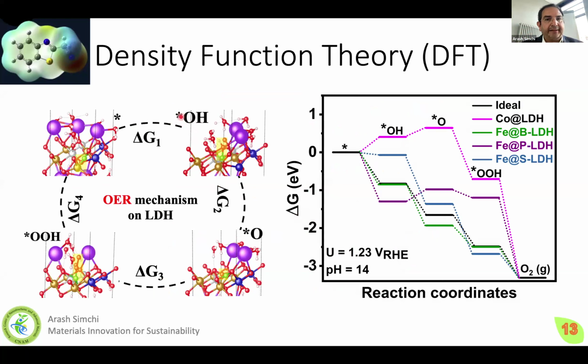OH star adsorbs on the surface, and then oxygen star is produced and makes it OOH, and then oxygen is created. So there is some energy behind that for the oxygen evolution reaction. And then we can calculate theoretically the delta G of each reaction depending on the type of catalyst, whether I use cobalt, iron, boron, phosphorus, or sulfur.